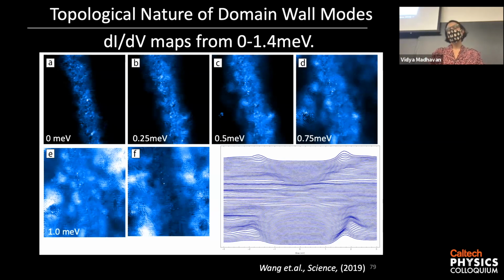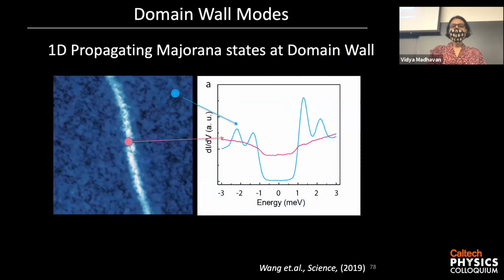Yeah, that's correct. So I think this paper, I think it's the Science paper, has calculations by Liang Fu as well. And Liang Fu's calculations show that for this material, I don't think there's any difference between the Caroli-de Gennes-Matricon states for an S plus minus superconductor and an S-wave superconductor. Because S plus minus is just the relative phase of superconductivity between different pockets. So if you just look at one pocket, it's just an S-wave superconductor.